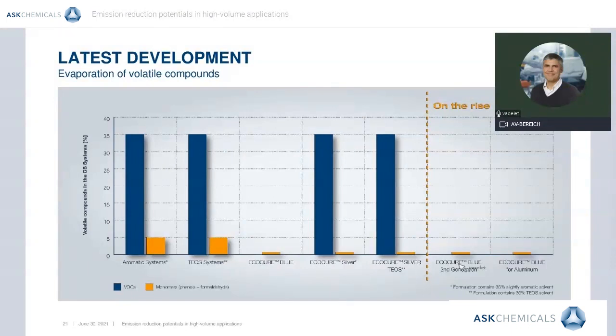We are also in the final stages of developing a second generation of ECOCURE Blue, which will be even more efficient than the first and should be on the market before the end of the year. In parallel, we are working on a new solution for aluminum application, which will be a VOC-free solution, which, unlike other Blue solutions, will generate less tars and will even reduce gas pressure well below Silver aromatic or TEOS solutions.